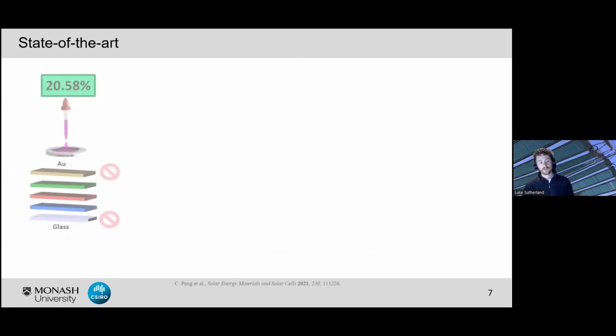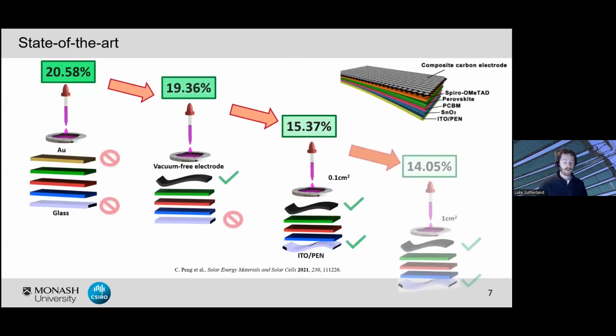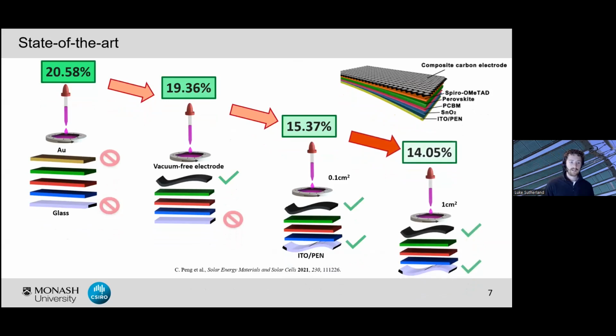And so various other alternative electrodes have been proposed: printed carbon, silver nanowires, even carbon and aluminium foil. But as I showed before, we see another similar trend starting to occur where these teams are able to fabricate highly efficient devices via these traditional methods, but then by introducing these vacuum-free electrodes,